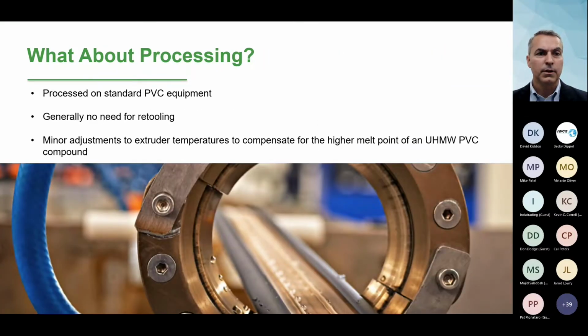So what about processing? It's got all this high performance. How does it run? Well, fortunately, Flexalloy compounds are processed to run on standard PVC equipment. There's no need to retool. The only adjustment that's required is to increase the extruder temperature to compensate for the higher melt point of these compounds, which are formulated with ultra-high molecular weight PVC. Aside from that, these are readily run on standard PVC equipment.